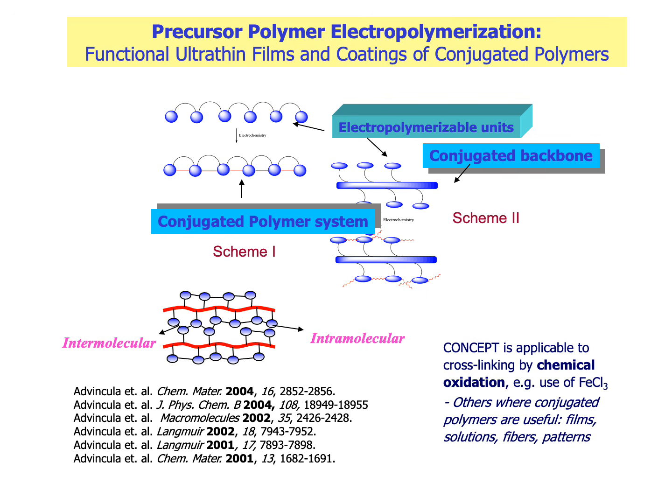So we pioneered the use of the precursor polymer approach towards electropolymerization of conducting polymers based on inter and intramolecular cross-linking, where a conducting polymer can be populated with electropolymerizable side groups and deposited as films.